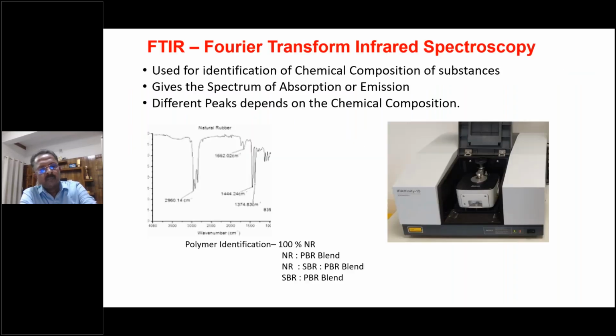Let's see FTIR. FTIR is mainly used for the chemical composition of substances. So every chemical composite has typical peaks. A typical NR spectrum is given. From this analysis, we can identify the polymer nature, whether the compound contains 100% natural rubber, or a natural rubber PBR blend, or a natural rubber PBR SBR blend, or a PBR SBR blend. So we can identify the polymer content. What kind of polymer is used for the tire tread rubber, from FTIR.